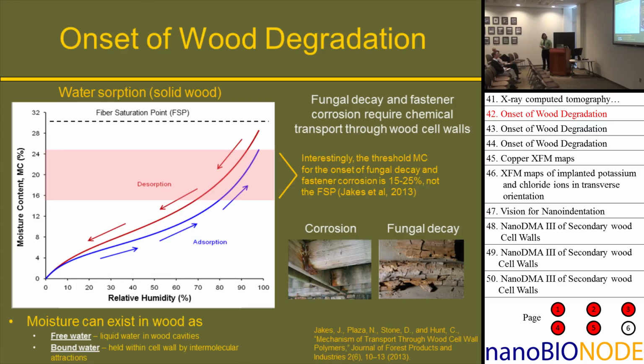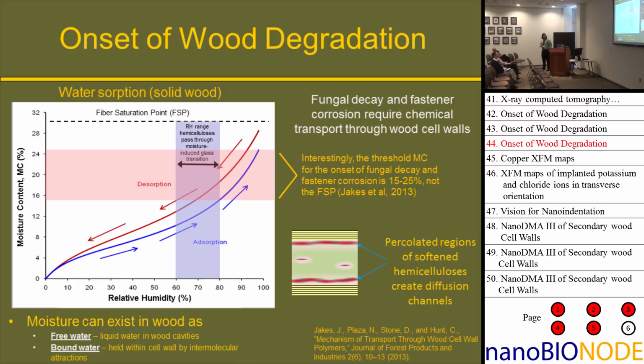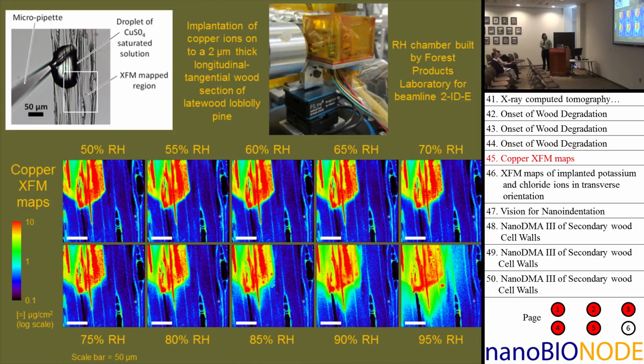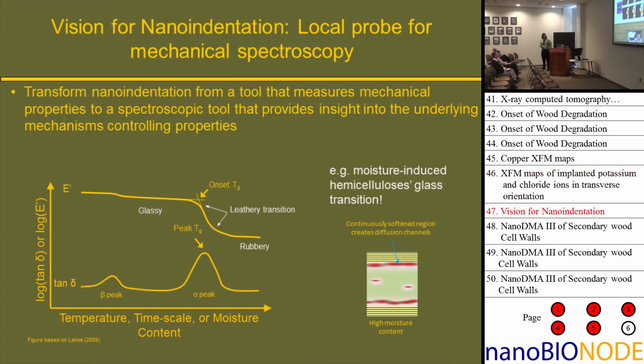So basically, degradation requires ion transport through the cell wall, and ion transport only occurs above a humidity that actually corresponds to what's believed to be the moisture-induced glass transition of the hemicelluloses in the cell wall. So we also design experiments to verify that there is a moisture threshold for ion diffusion in wood cell walls. This is using an environmental chamber inside the fluorescence microscopy beam line at APS. You see that at low humidities, no ion diffusion; at high humidities, lots of ion diffusion.